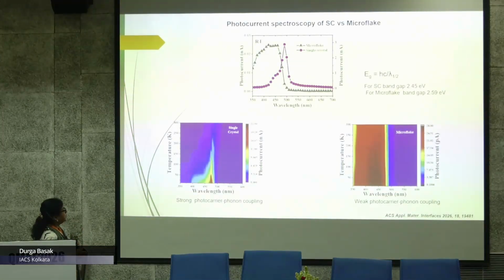For the single crystal, we get a sharp peak at around 490, and as we decrease the wavelength, that means increase the excitation energy, then the photocurrent decreases, and this decrease is due to the surface recombination. But in case of microflake, as we decrease the wavelength, that is increase the excitation energy, you don't find any decrease. More or less the photocurrent remains the same.